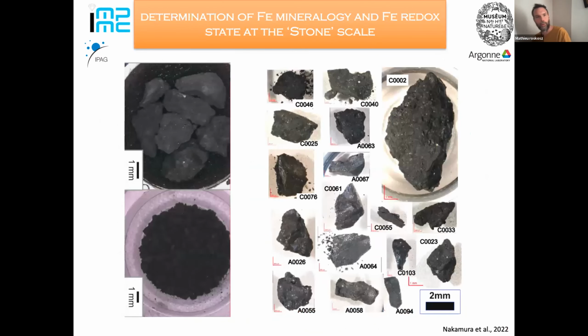So now, focusing on the samples, this is how the Ryugu grains look. So it's black. It looks like coal, basically. This was expected because we had spectra at the time of the recovery of the grains indicating that the samples were probably close to the carbonaceous chondrites, like Orgueil or Alais or maybe Murchison. So it's black. There are no big crystals that you can see with the naked eye.